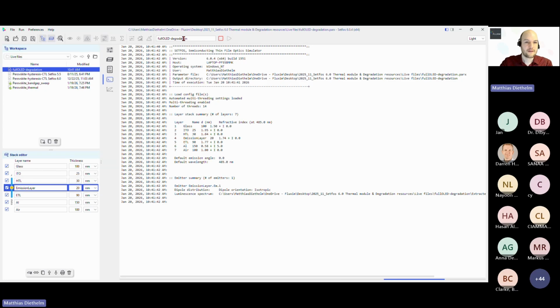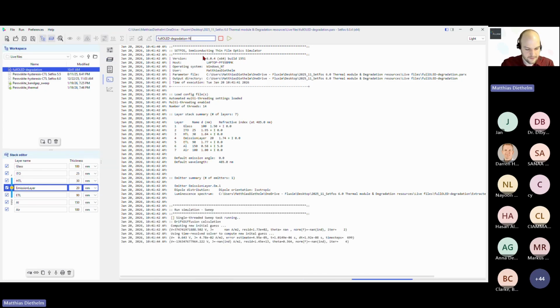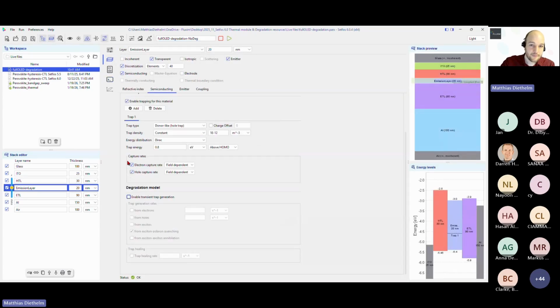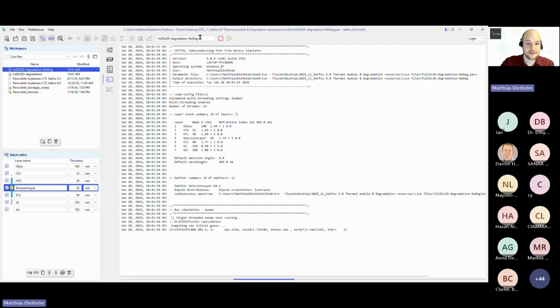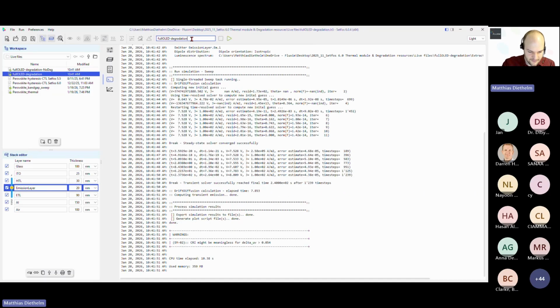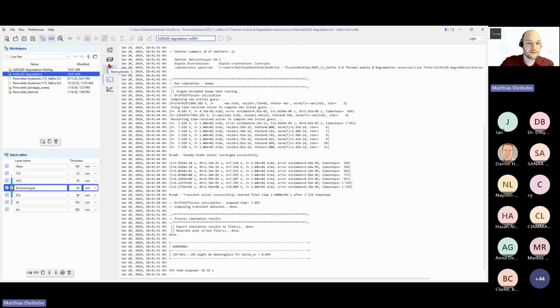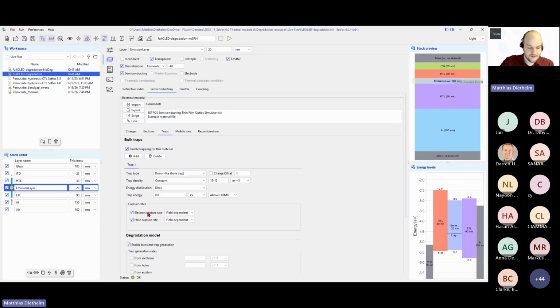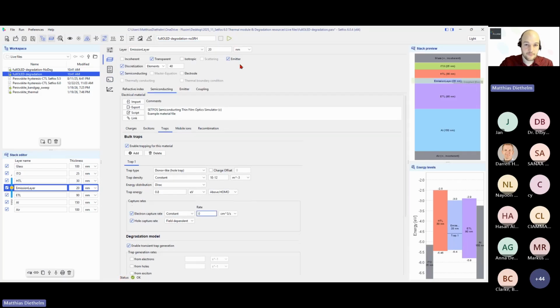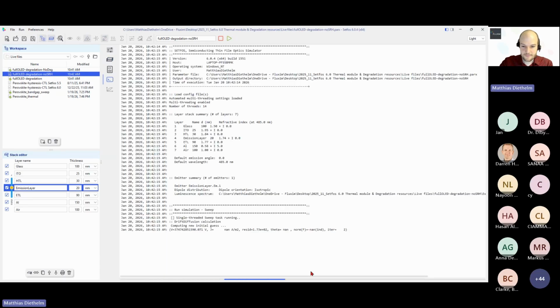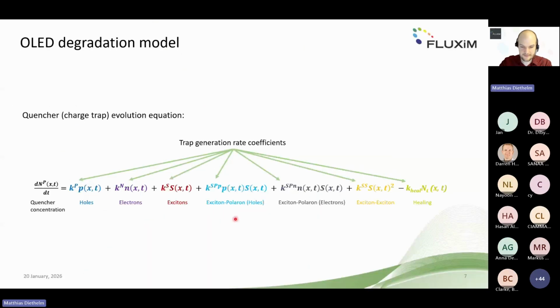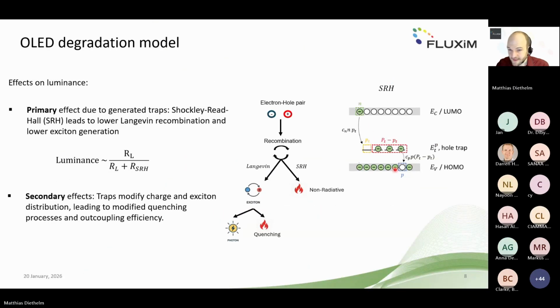So the first thing we could do while this is running, I turn off the degradation model to see how this looks like in comparison. So the files are generated here on the side and we can compare it later. And what I also do now as a comparison, I turn off the Shockley-Read-Hall recombination. I will explain in a second what this means. What I'm doing is I'm setting here the electron capture rate to 0. So what I did now, just to show you this, is in the Shockley-Read-Hall model, I turned off here the electron capture rate, but what's still going on is that holes are still trapped. So you still get the hole trap density, and this hole trap density also influences the whole system.